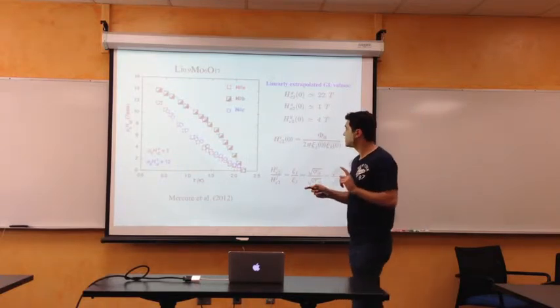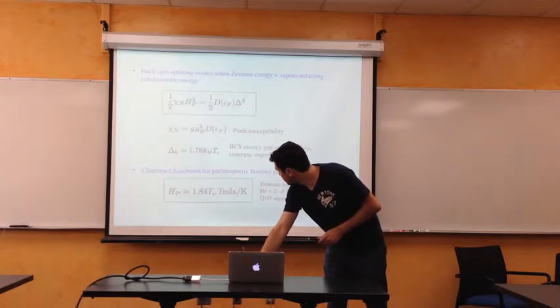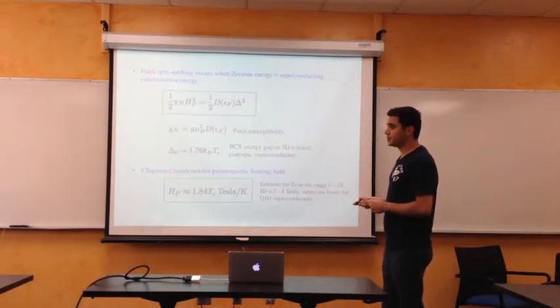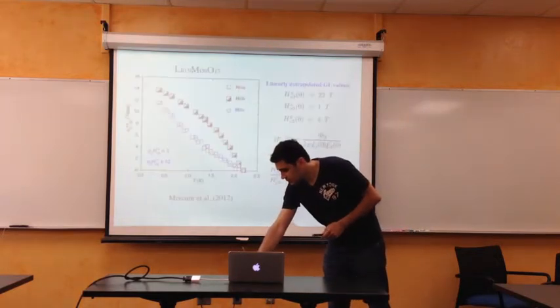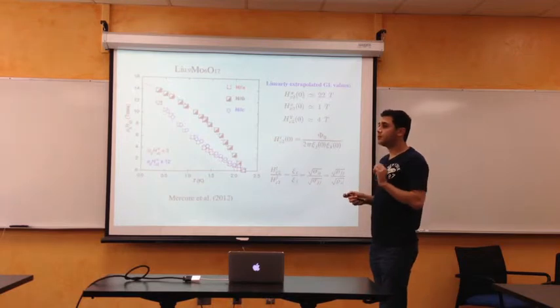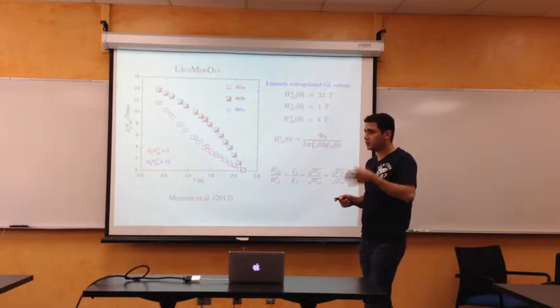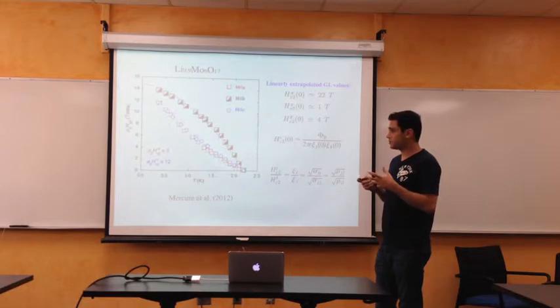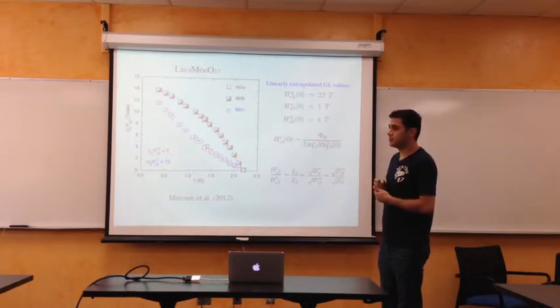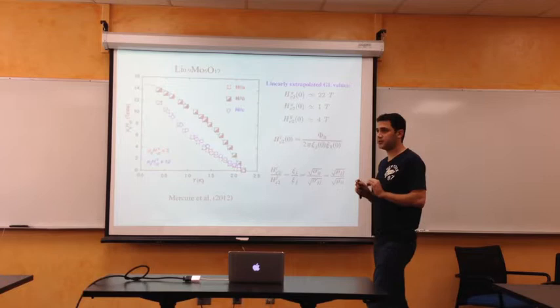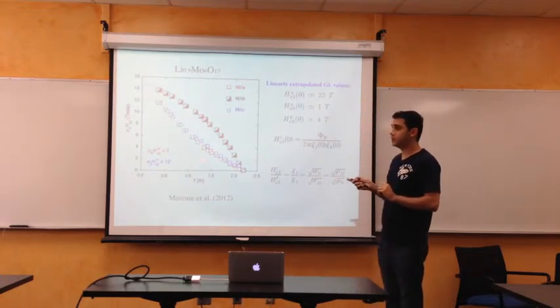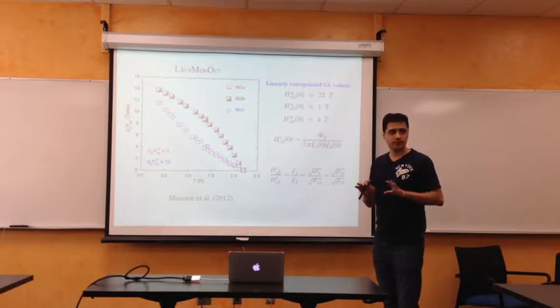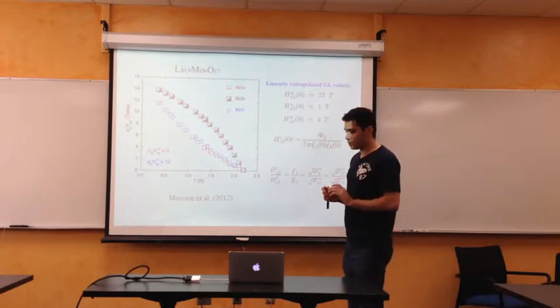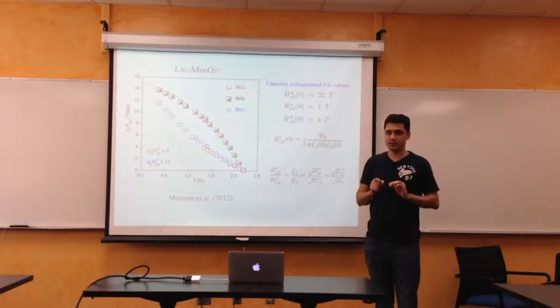I also have to mention that the formula for the paramagnetic limit presented here is for a 3D superconductor. But in this case, the value of about 3 Tesla has been experimentally determined from the actual numerical values of the Pauli susceptibility and the specific heat discontinuity, and so on. So it's an experimentally extracted result, 3 Tesla, and it's 5 times lower than the maximum field theory. So we have to resolve some serious inconsistencies if we assume that this is a regular spin singlet type of pairing.